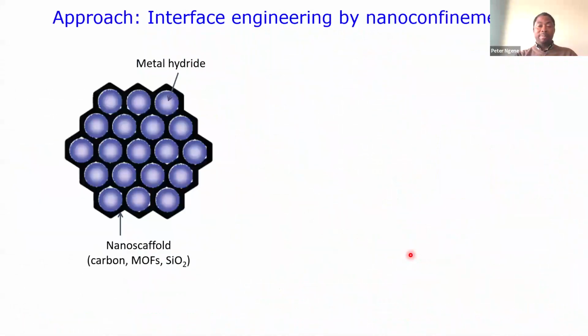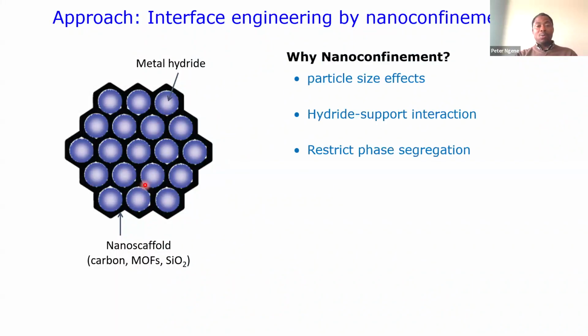So our approach then was to do what we call nano-confinement. So why do we want to do nano-confinement? First of all, what is it? We have a metal hydride and we have a scaffold material, in this case something like carbon. This is just a cartoon. Then we can put this metal hydride in this small porous carbon. We need a scaffold that is quite porous, so we can actually put all this metal hydride in there. It can be carbon, it can be a metal organic framework, or silica. But because these metal hydrides are very reactive with MOFs and metal oxides, as you're going to see, we started with carbon.